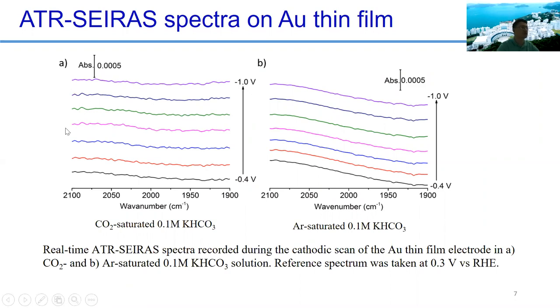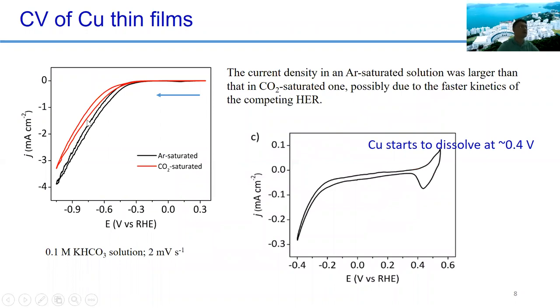Okay, so this is an in situ FTIR signal at different voltages. This is a carbon dioxide saturated 0.1 molar potassium bicarbonate solution, and this is an argon saturated solution. You can see that on gold thin film, there's nothing, no signal, in this wavenumber range. So that means the gold has no impact on our investigation. And then we can do our in situ experiments.